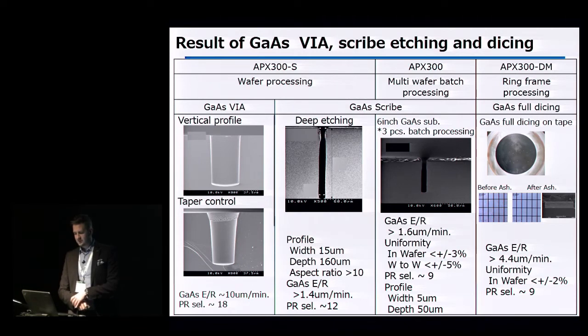This is some more examples of our capabilities, able to etch vias. This is our dry etching machine, so it's the same machine, but used just the bare wafer instead of being on the dicing frame and tape. But this is our plasma dicer on the end. We are also able to dice gallium arsenide wafers with faster than 4.4 micrometers per minute dicing speed and less than plus minus 2% uniformity on the whole wafer.